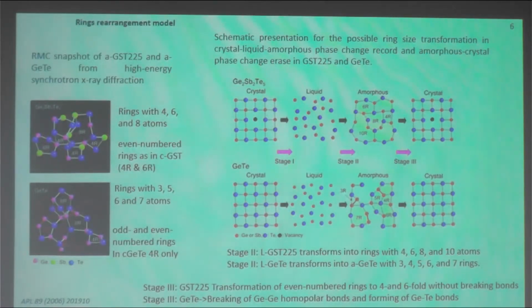The next model is based on ring statistics, or the fact that the amorphous state is built of small units, different rings. We know already about this. This is for your recap, a structure model from RMC and synchrotron data for GST225 and germanium telluride. In the amorphous state there are different types of rings, mostly even-numbered rings in GST, like 4, 6, and 8. In germanium telluride, there are a little bit more ring types, like 3, 5, 6, and 7 atoms.